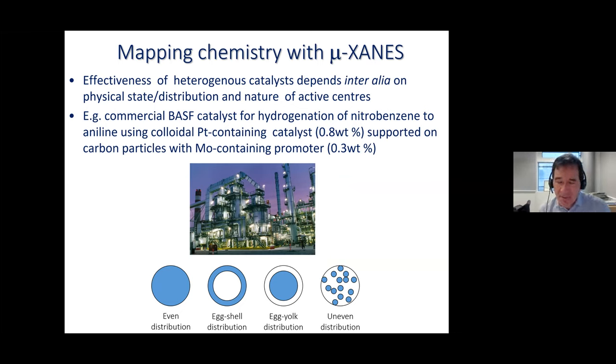So it's very important to understand the mechanism of the particular catalyst, and also to devise ways of spreading a small amount of catalyst as thinly as possible. If you just had a lump of the platinum compound, its surface area would be very low, and it would have a very low efficiency per kilo of the material. The way in which we make these materials most efficient is, first of all, to produce them in chemical forms where the individual molecules are as efficient as possible as a catalyst, and then to distribute them as finely as possible over the surface of a supporting powder or a porous material.